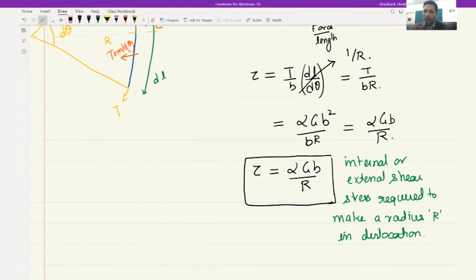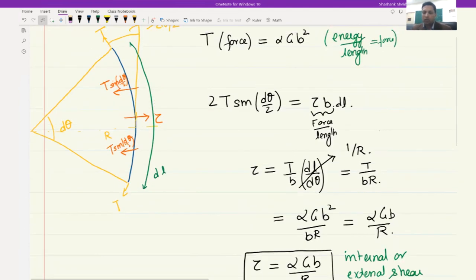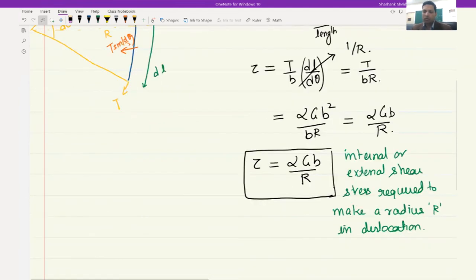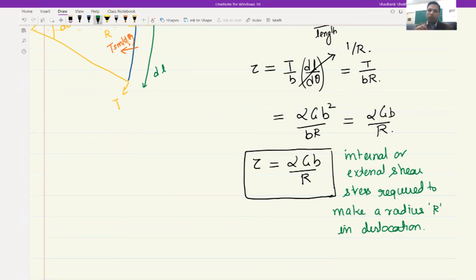This is the consequence of the energy associated with the dislocation: the line tension means you must apply at least tau = alpha*Gb/r to create a given radius of curvature. A very small radius requires a very large shear stress, because you are creating a tight loop. Conversely, a very large radius — meaning nearly straight dislocation — requires very little shear stress. This is consistent with what we know about dislocations and gives a clear relation between shear stress and radius of curvature.